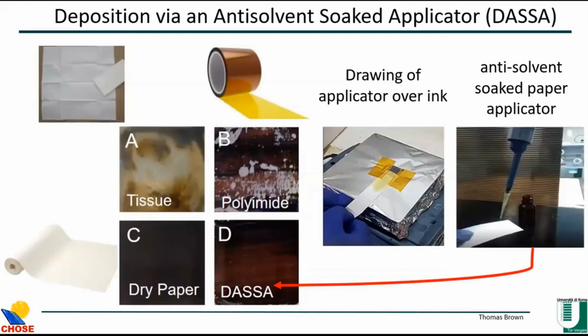So as I said, we tried different soft applicators. This was the tissue which we started with, polyimide. Tissue absorbed most of the precursor solution, so nothing was left on the substrate. Polyimide isn't absorbing enough, so it wouldn't help in forming a nice film. With a piece of dry paper, you get nice thick films, but not very uniform. And by first soaking the paper in an anti-solvent, not the solvent, but the anti-solvent, you get better films macroscopically.